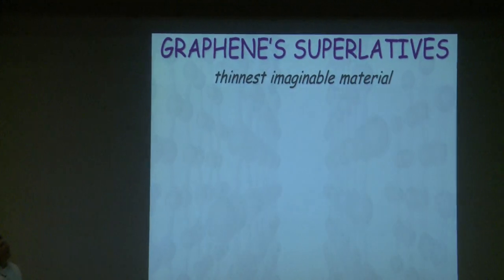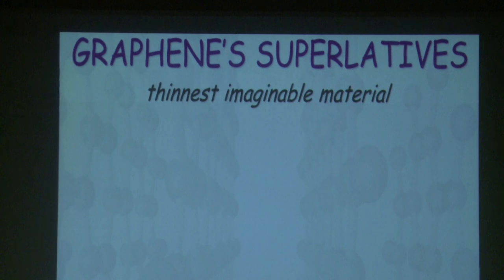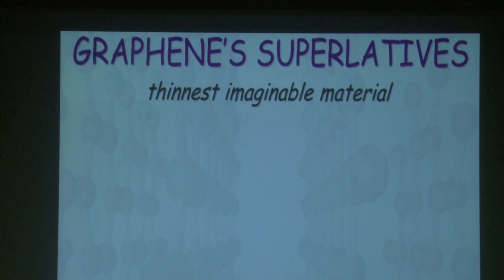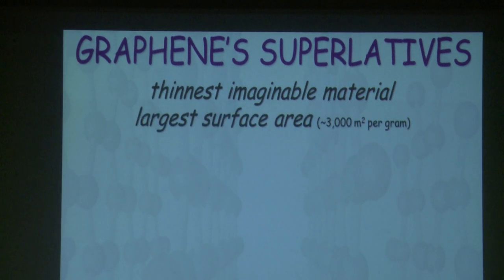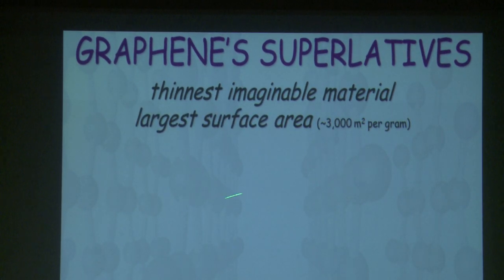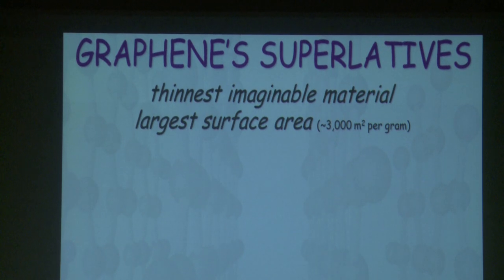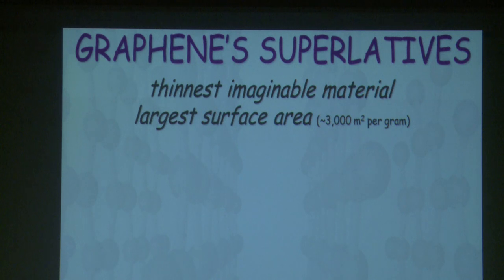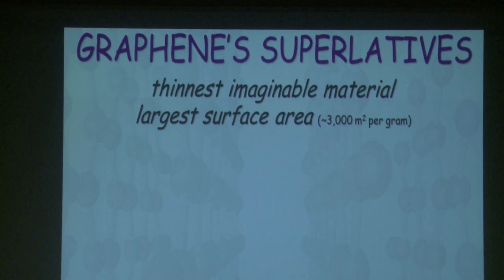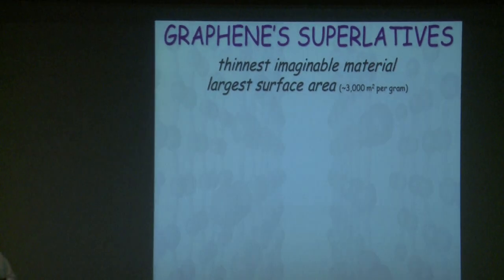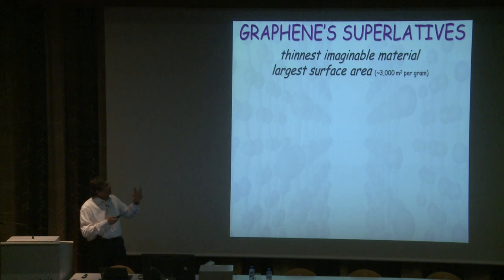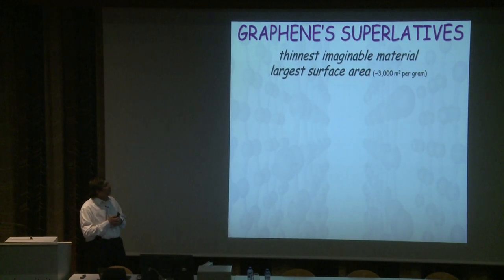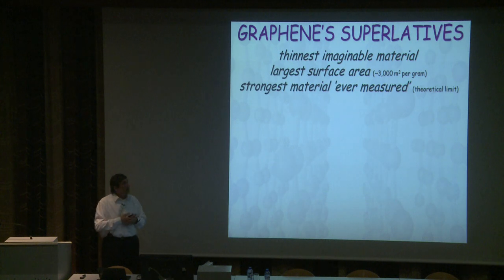Of course, no material can probably be thinner than one atom, unless you go into science fiction. And it's so thin that one gram of this material is enough to cover the whole football pitch. You know, in Manchester, we measure everything in football pitches. Those properties come from the fact that it's so thin. But then you start to measure. And it turns out that this is the strongest material ever measured, not in our research but by other people. Of course, you have to take into account that it's very thin.